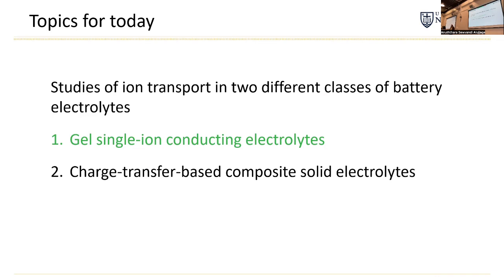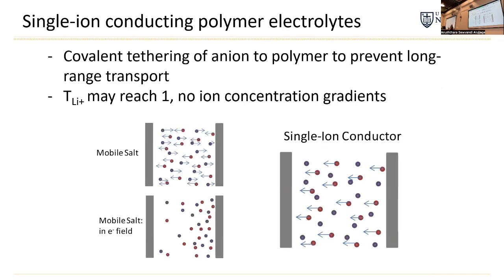Thanks very much. All right, so first, what is a single ion conductor? A single ion conductor is an electrolyte where only one of the ions moves. Now, if you imagine any fluid that you dissolve salt into, like a commercialized lithium-ion electrolyte, you have multiple species. You at least have two different species, a positive species and a negative species. And in the presence of the electric field, both of those species will respond and they will move. And when that happens, because only one of the species is reactive with the electrodes, over time, you will develop a steady state ion concentration gradient here.